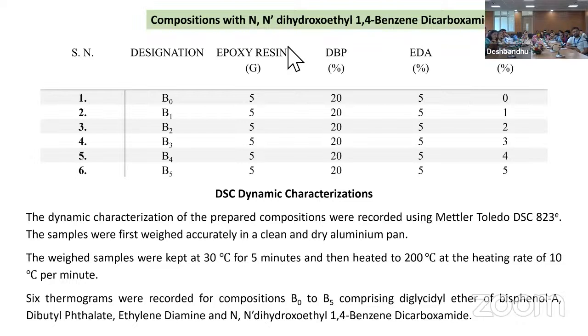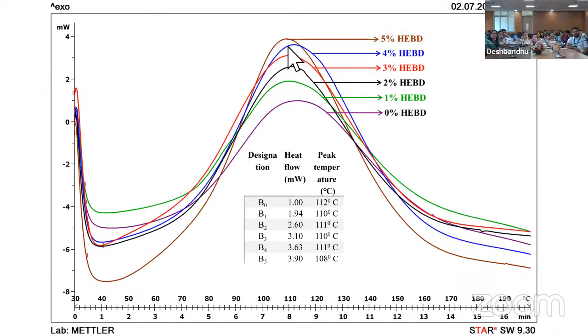So 6 thermograms were recorded, from B0 to B5, comprising HEBD. Here, all the thermograms are overlaid. We can see in these overlaid thermograms that at 0% HEBD, in the table, the heat flow is mentioned, this is milliwatt 1. Then at 1% HEBD, 1.94. It is gradually increasing as we are increasing the concentration of this monomer.